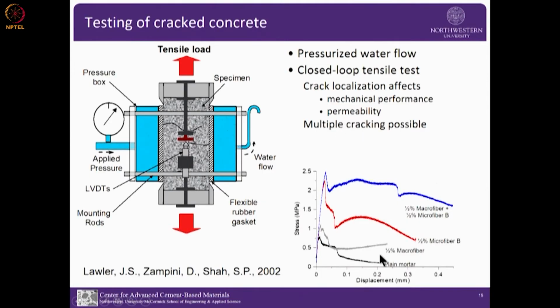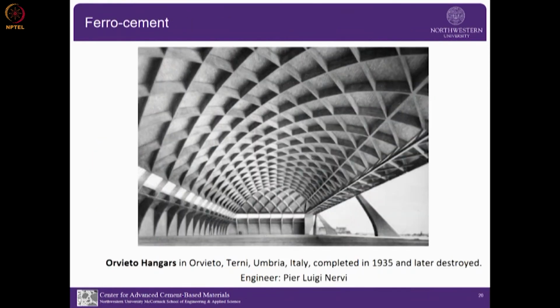So here is the stress displacement of plain mortar, and here is 0.5% of steel macro fiber. And as I showed you, it doesn't really change much, except post peak. Now this is 0.5% of micro steel fibers. We asked Bekaert to make just the microfiber for us, I think it was 30 micron in diameter. And then of course when you combine them, you can get both high peak strength and a strain hardening response. So that was what I wanted to talk about, hybrid.